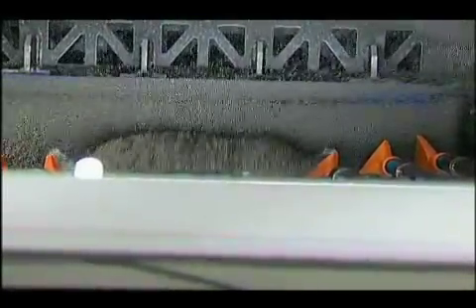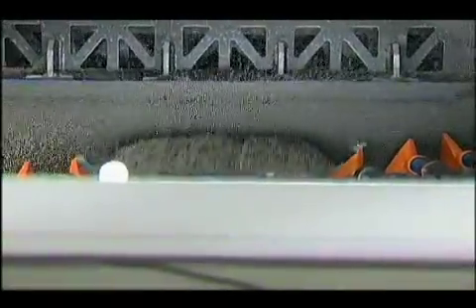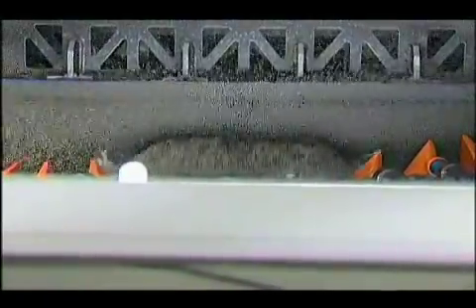The rebounding of the media particles created by the oscillating fixtured part results in a fast, high-energy cleaning action. The media flows around the part and through simple or complex passageways with equal effectiveness. The cleaning action is enhanced by the use of various environmentally safe cleaning compounds that can be matched to the desired results. Vibration of approximately three-sixteenths of an inch or five millimeters produces 18 to 24 g-force, providing a precision flow of media around and through the fixtured part.